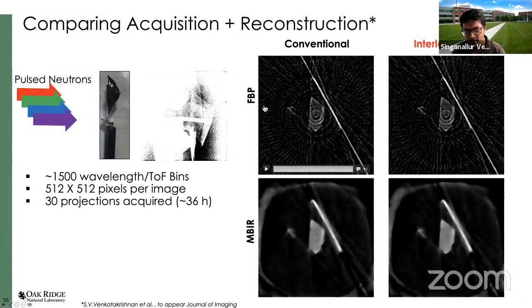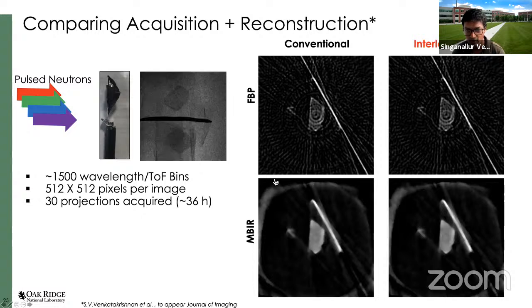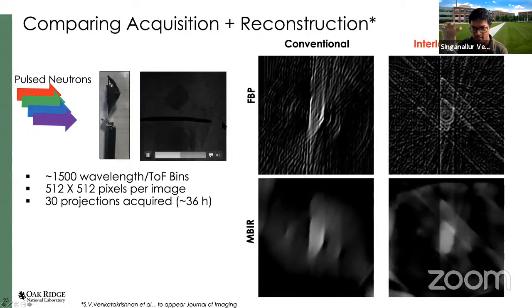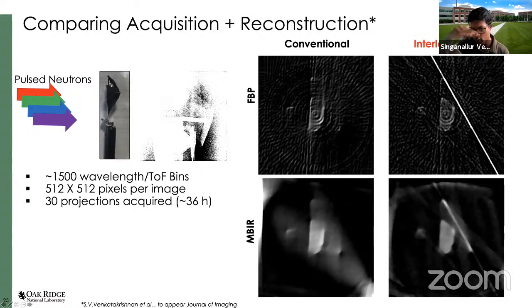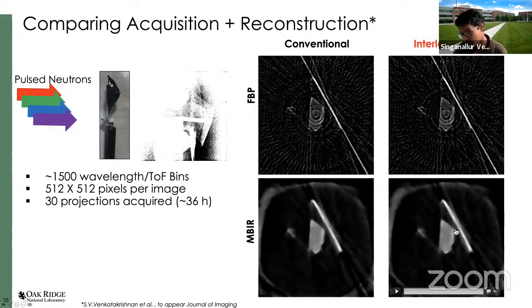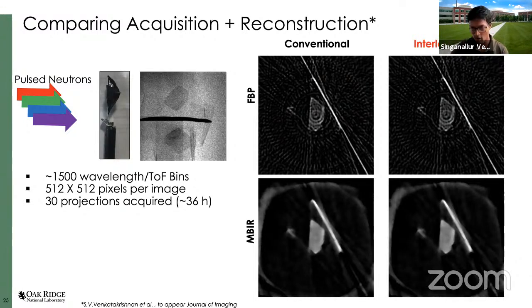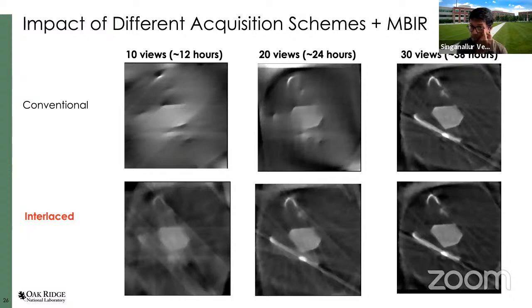And what we can see is that by using a combination of the model-based methods along with this interlace scanning, we can get higher quality reconstruction. So I'll play this again. What you'll see on the right is the evolving reconstruction, a single cross section. And you're able to see these cross sections best, or earliest, for the sample when you're using an interlace scan with the model-based method. So it's useful. It's just a useful tool for end users who are using these shared instruments to have this feedback. And it is the combination of this better scanning and reconstruction that helps.